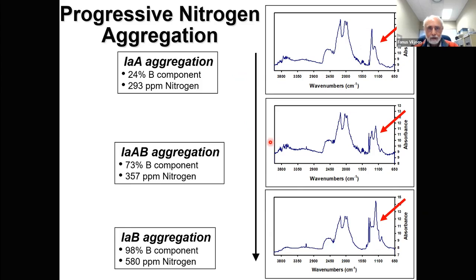This is another diamond that I've selected to illustrate what a stone with somewhat more aggregated nitrogen would look like in terms of its infrared spectrum. This is known as an IaAB aggregation state. So this would be classified as a IaAB diamond. It contains 73% of the nitrogen in the highly aggregated B component, for this stone, which contains on the order of 400 ppm nitrogen. And you can see that this peak, particularly in the nitrogen region, is now more pronounced.